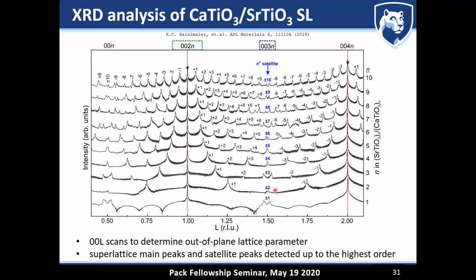And the other thing that you can see is that there's a splitting of this nth satellite. And sometimes the splitting is very large. For example, here for the n equals 3. There's also somewhat of a split for n equals 2. This is the one that we just looked at. While in other cases, there's barely any split. For example, n equals 5 or n equals 4 is a very small split. And this split is really coming from the intermixing that you have at those interfaces. So we were able to see all of these highest order satellite peaks in these superlattices.